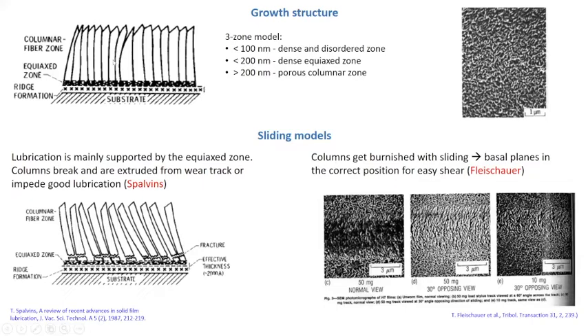And if you continue in the deposition, you have the growth of this third layer, which is composed by a columnar structure where the basal planes of MoS2 are perpendicular to the surface. And still from the work of Spalvins, here you can see a view with the SEM of the surface of a PVD film, where you can see this particular needle-like structure, which represents the top of the columns in the sketch.